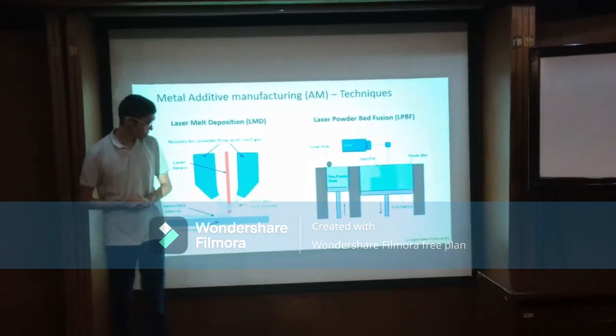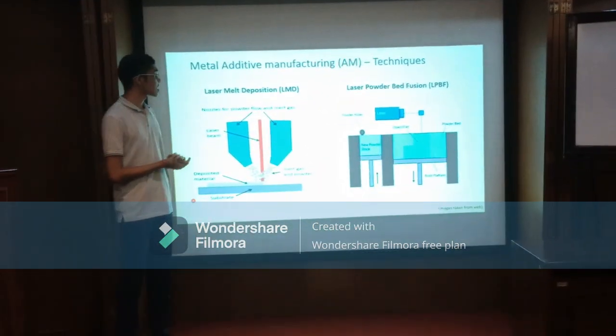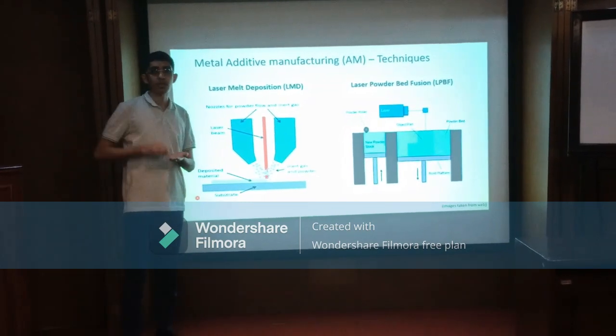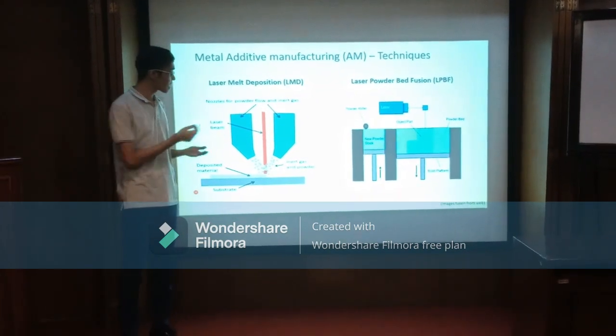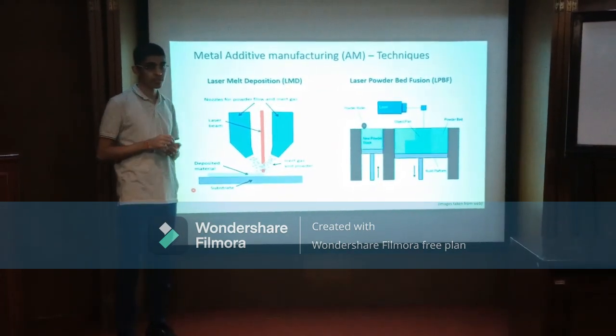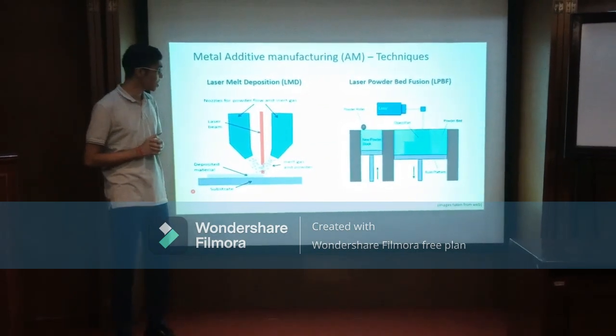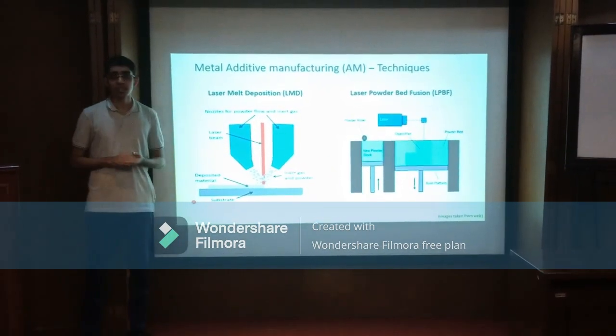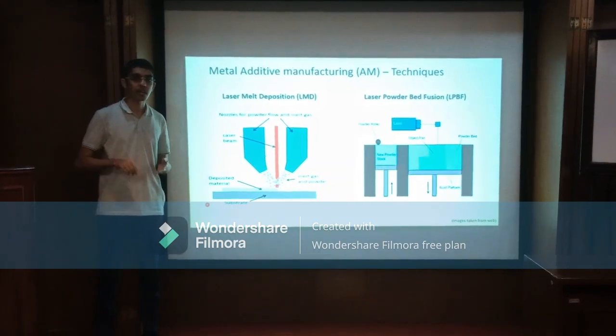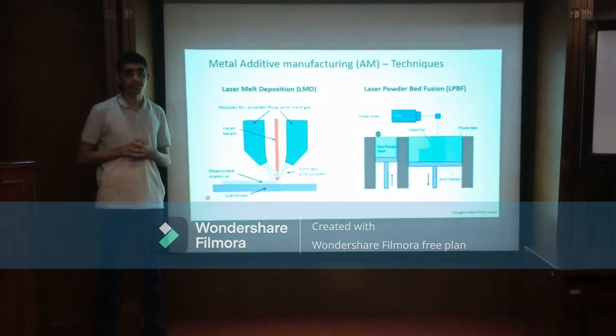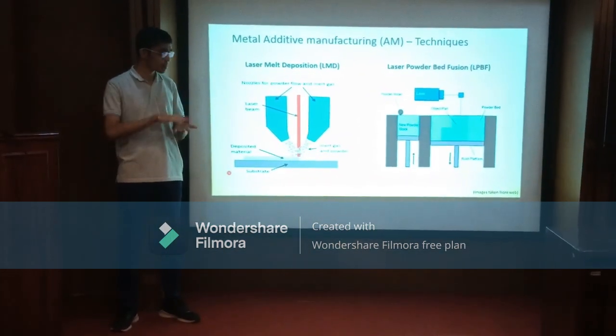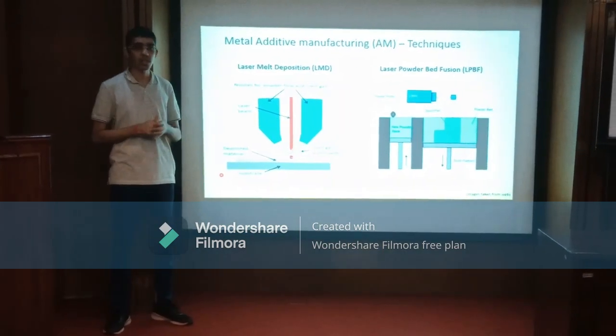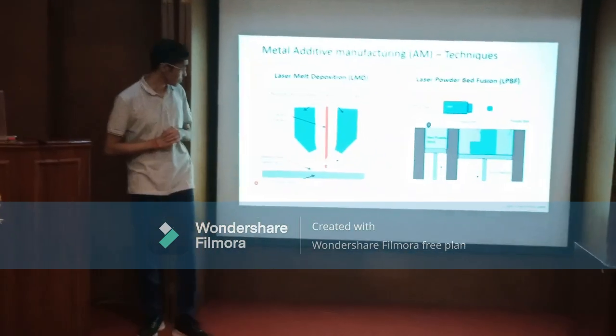The second technique, laser powder bed fusion, it also uses laser, but here we have a bed of powder. So in this case the laser scans over the bed of powder in a similar way, and the metal melts and then solidifies. But once a layer has been made, then the next layer of powder is added, and again the laser will go over that. So in this way, layer by layer again the deposition happens and we will get the final component.